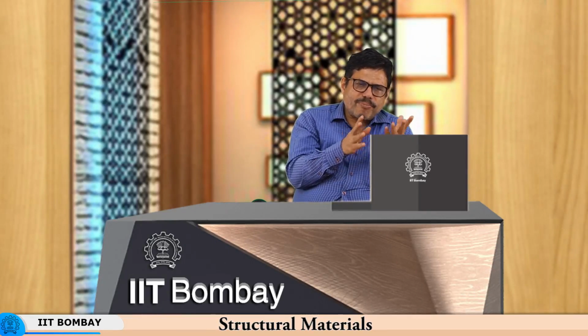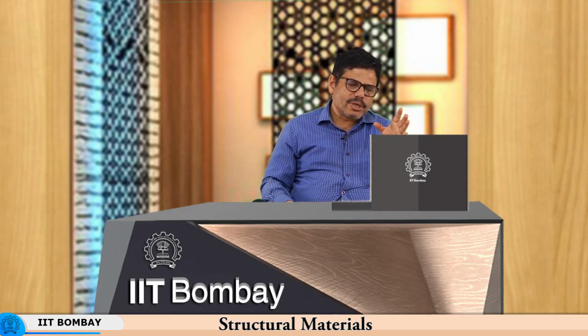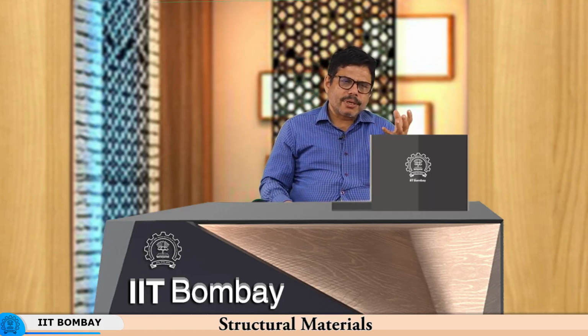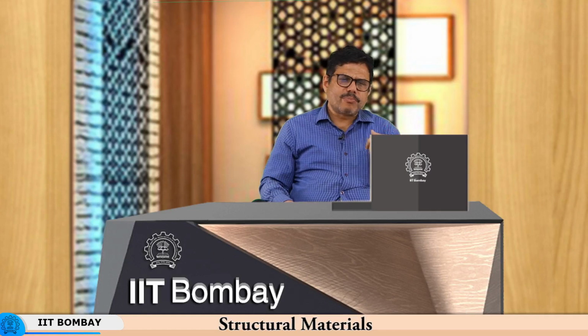So, naturally there is a small amount of plastic deformation taking place, and so the residual stress that was present gets relieved because it has been dissipated in generating some amount of local plastic deformation. So, you do not see it on a global scale, you do not see it at a macroscopic scale, but internally the stresses get relieved in the material. Of course, the material has to be fixtured and put in the right orientation. So, for stress relief you need to put it in a proper location, orientation, etc. Then you go on heating it even further, you keep it for a longer period of time, it can even recrystallize, meaning the older grains can be replaced by the newer grains.